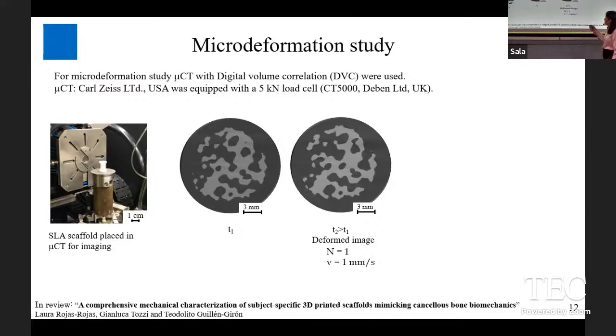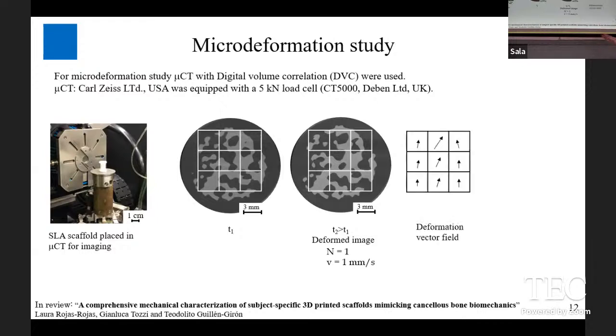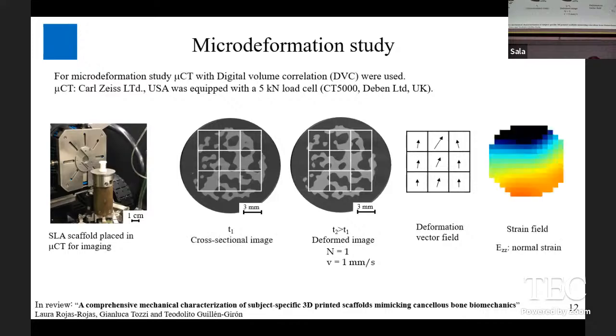After a while, we can deform the volume, and as you can see, there is a difference between the first volume and the second volume. So by using an algorithm and computer software, it is possible to divide the volume into small subvolumes, and then track the grayscale between one another, and this way we can obtain a deformation vector field, which gives us how the sample behaves under this loading stress. And moreover, the program is able to do a strain field.